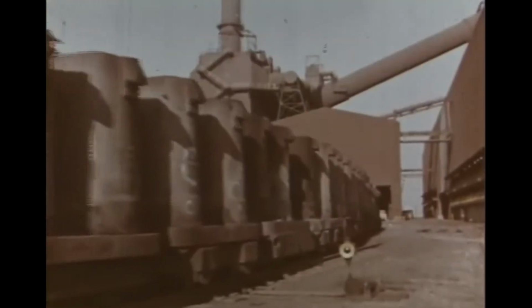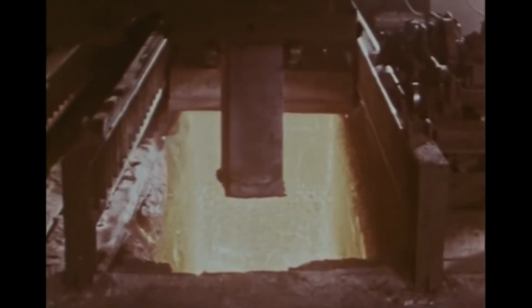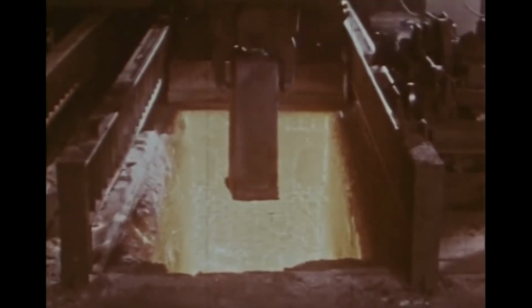The ingots are allowed to cool in the molds long enough for a solid shell of steel to form around the still molten center. After the molds are removed, the ingots, still extremely hot, are lowered into a gas-fired soaking pit. Here, after soaking up heat for several hours, they will be white hot again, at a uniform temperature of about 2,400 degrees, inside and out, just right for rolling.